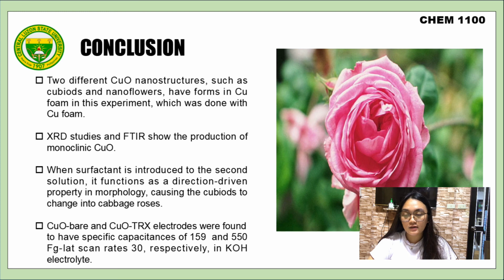XRD studies and FTIR show the production of monoclinic copper oxide. When surfactant is introduced to the second solution, it functions as a direction-driven agent in morphology, causing the cuboids to change into cabbage roses. Copper oxide bare and copper oxide TRX electrodes were found to have specific capacitances of 159 and 550 F/g, at a current density of 30 A/g, respectively, in potassium hydroxide electrolyte.